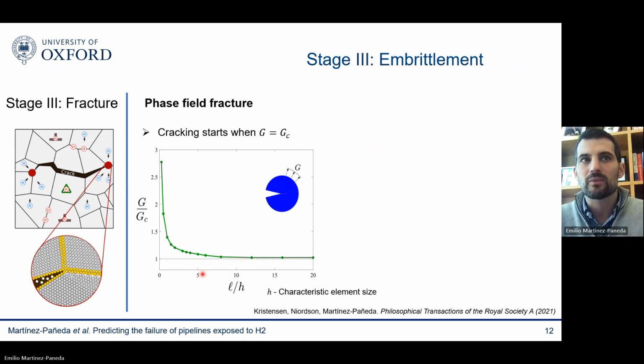We see that an element size that is 7 to 8 times smaller than the length scale is all we need. And once you have that sufficiently fine mesh, you get the same result. And what you see is that this result is precisely what you expect from fracture mechanics. So this ratio approaches 1, which means that cracking is initiating when your stress intensity factor is equal to your fracture toughness, or when your energy release rate is equal to your critical energy release rate.